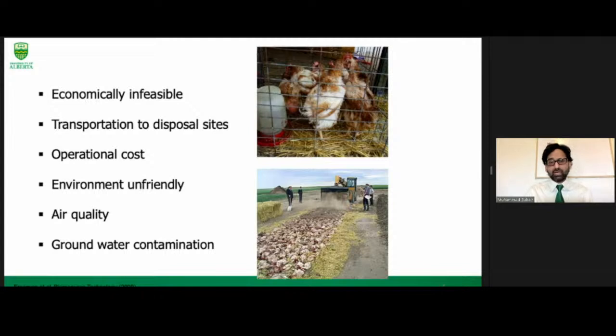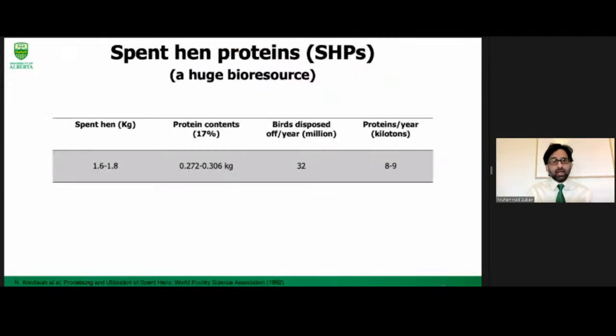And most importantly, the disposal of these spent hen proteins is environmentally unfriendly and creates problems related to air quality and groundwater contamination. We analyzed the spent hen and found that the whole spent hen weighs 1.6 to 1.8 kg in total. In this total weight, the protein content is 17%.